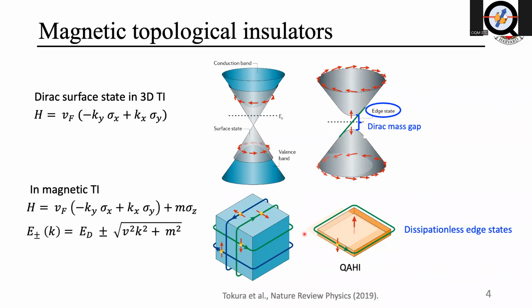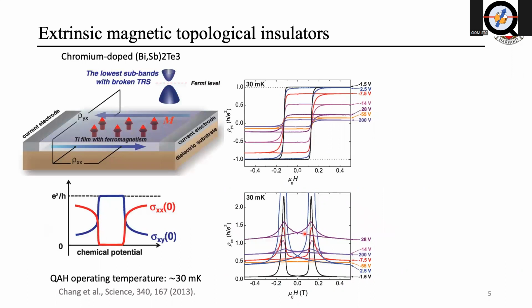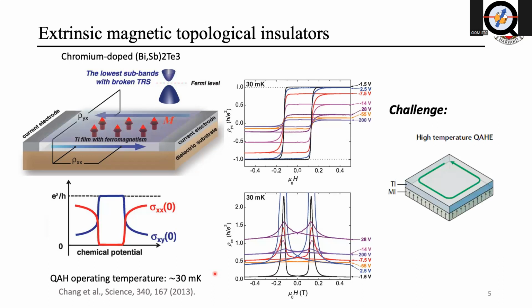Okay, so in the early days, people designed the magnetic topological insulator by doping the topological insulator with external magnetic atoms such as chromium. So here, this discovery in 2013 by Cui-Zu Chang, they discovered that in chromium-doped bismuth antimony telluride, they can see this quantum anomalous Hall effect, which is signified by the zero magnetic field plateau in Hall conductance or resistance. However, in this extrinsic magnetic topological insulator, the quantum anomalous Hall operating temperature is extremely low. It's only about 30 millikelvin. So the next big challenge would be, how are we going to develop a high temperature quantum anomalous Hall insulator, or how are we going to observe the quantum anomalous Hall effect at a high temperature?